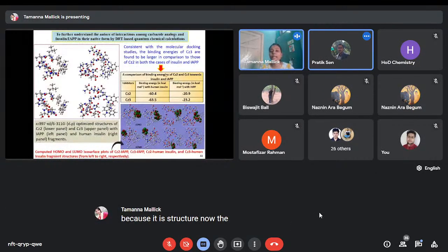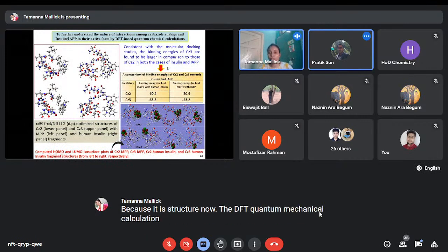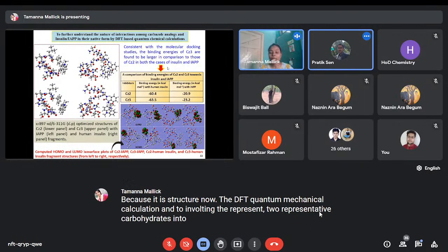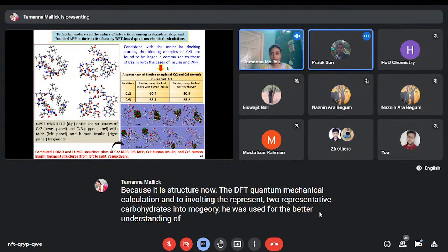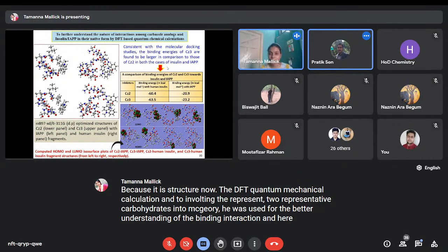Now, the DFT-based quantum mechanical calculation involving the two representative carbazoles, CZ2 and CZ3, was used for better understanding of the binding interaction. And here, CZ3 and CZ2 both have the N-methyl group, but unlike CZ3, CZ2 lacks the formyl group at the 3 position. Hence, from the binding energy value of CZ3, it indicates that the formyl group plays a key role in this purpose.